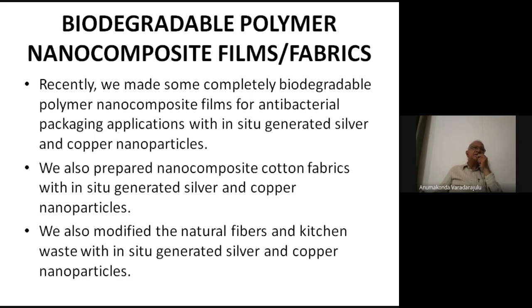In order to avoid that, we devised our own method of in situ generation of these metal nanoparticles inside the matrix. Instead of making them outside and then dispersing, we generated the particles inside the matrix itself so that it will be a single-step process, namely in situ generation of these nano materials inside the matrix. We made both the films and also fabrics, nano composite fabrics for hospital applications.